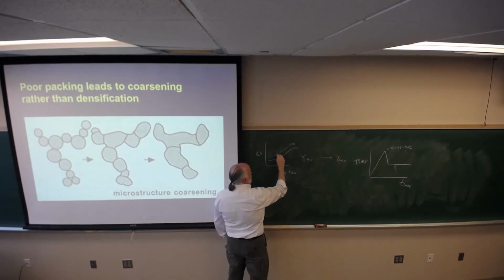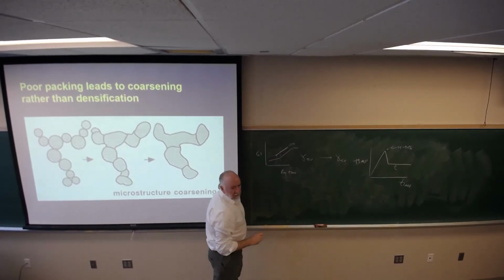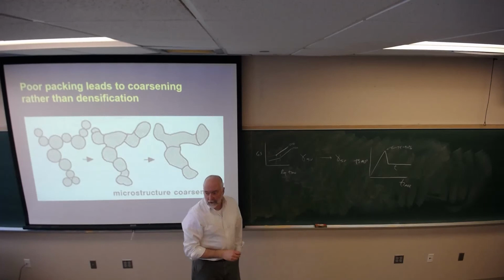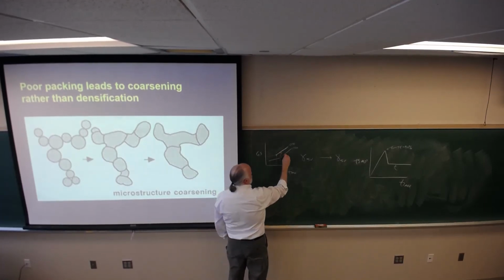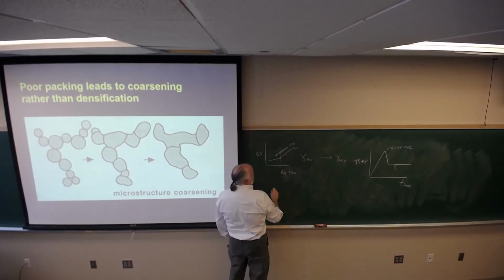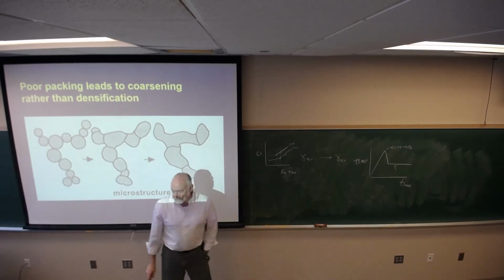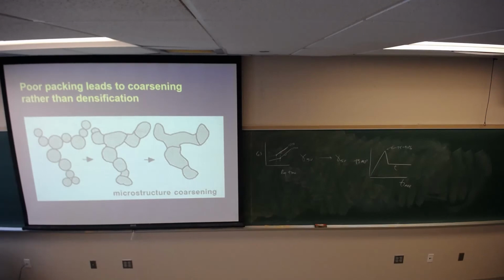When densification occurs, the grain growth is the same. The slopes of these lines are similar, but they occur at different times. This is the point where densification occurs. So once the system densifies, grain growth is free to take off. Otherwise, what happens is the pores stop that grain growth.